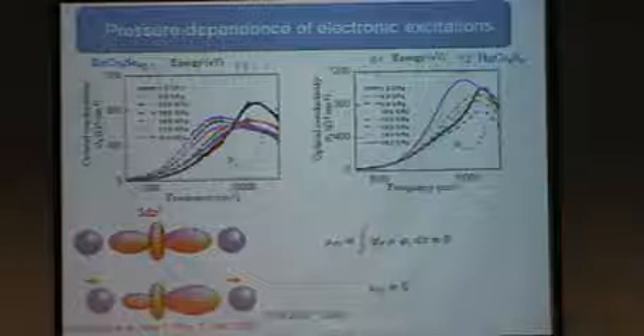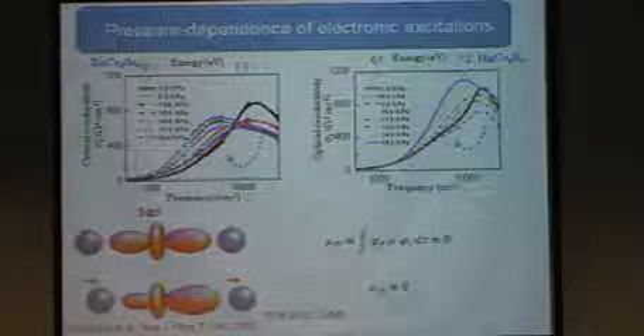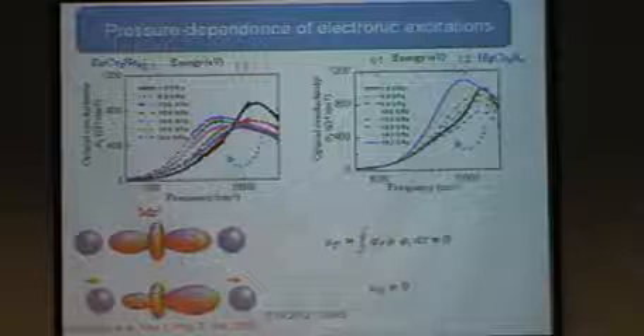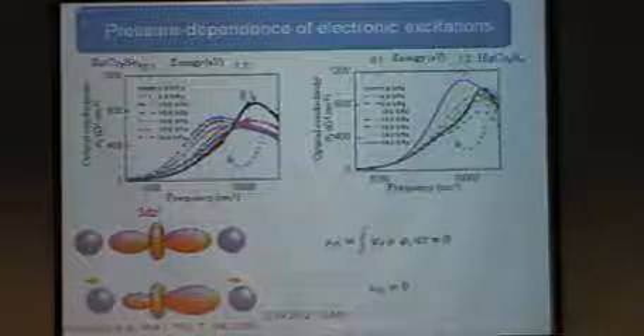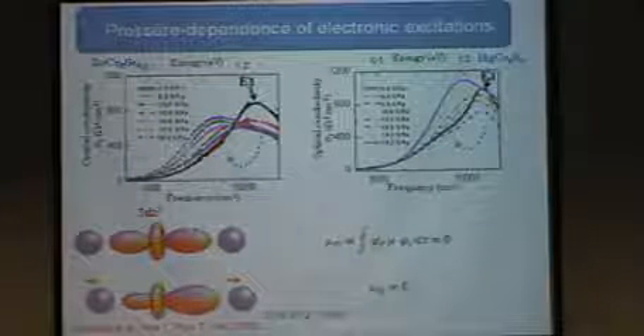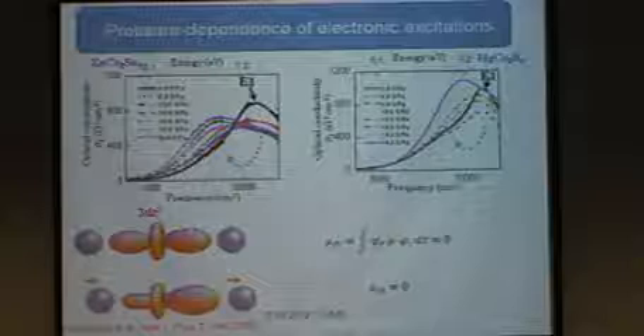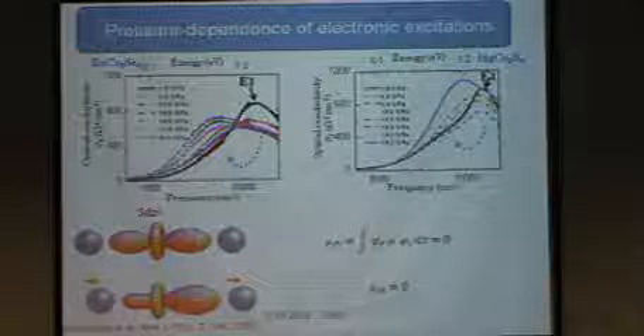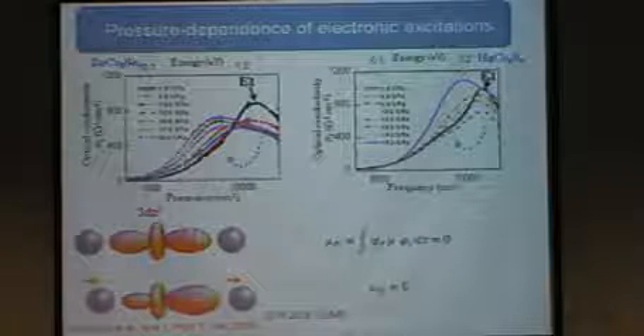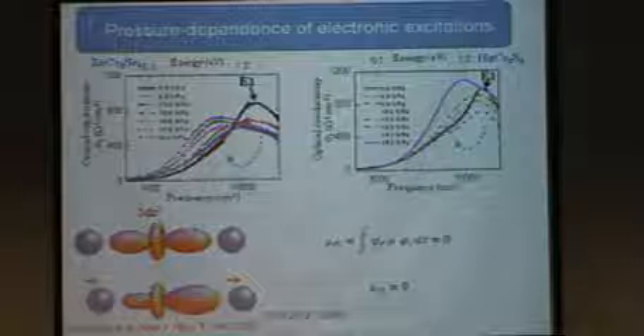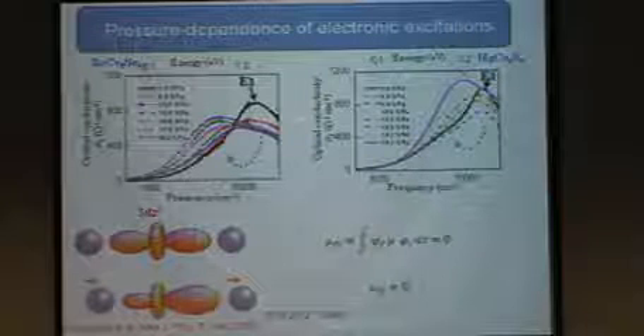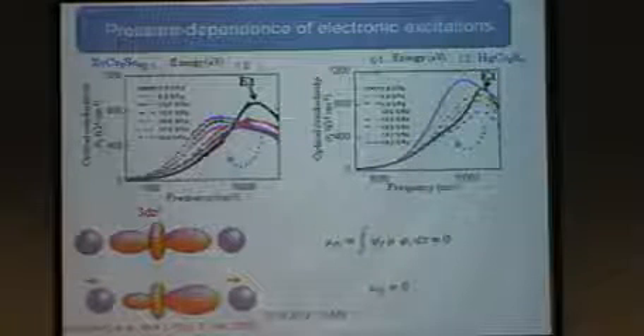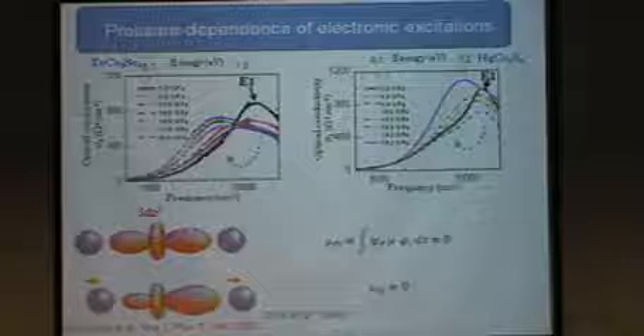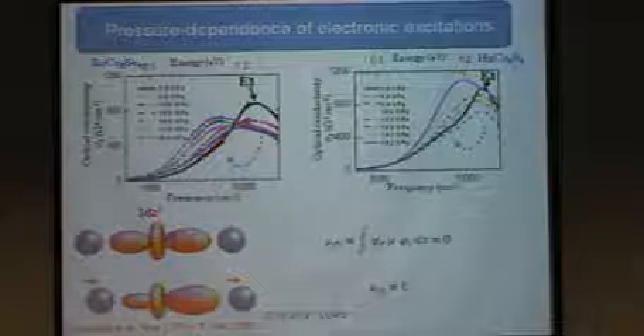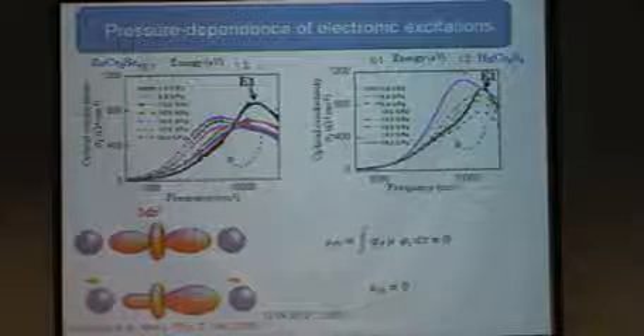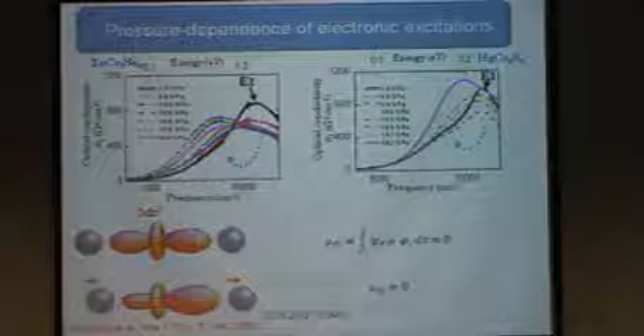First, with increasing pressure, the spectral weight shifts towards low frequency. And if you see the first measured pressure at 1.0 GPa, there is a prominent band. And this band, we interpreted it in terms of d-d on-site crystal field excitations. By spectroscopic selection rules, if you have a centrosymmetric complex, like you have